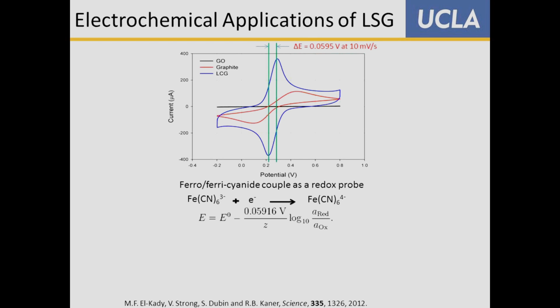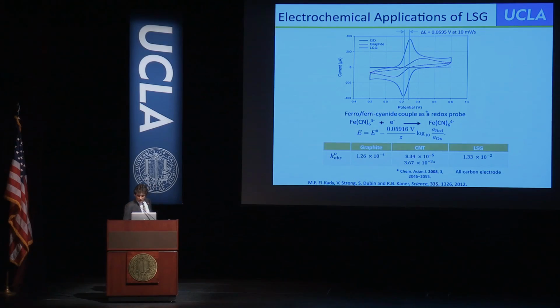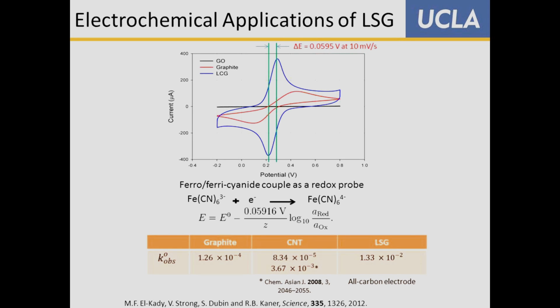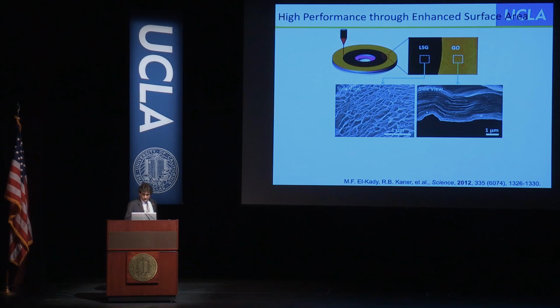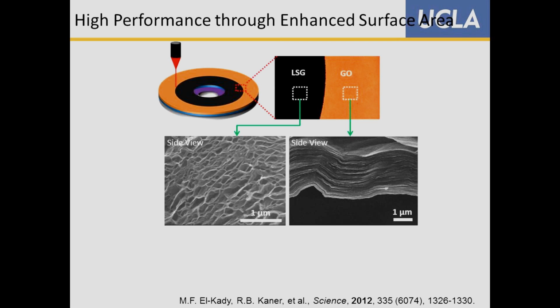So it's actually a legitimate measurement, but it says that electron transfer on a single sheet of graphene is extremely fast. And in fact, when he did the calculations, moving charge on graphene is at the rate of 10 to the minus 2 centimeters per second. And it's 100 times faster than graphite. So at that point, we realized we had a really good electrode material, and we needed to start making use of it. And so we used LightScribe, and instead of drawing a pretty picture, we just told it to darken the whole thing. And so here's laser-scribed graphene versus the graphite oxide.